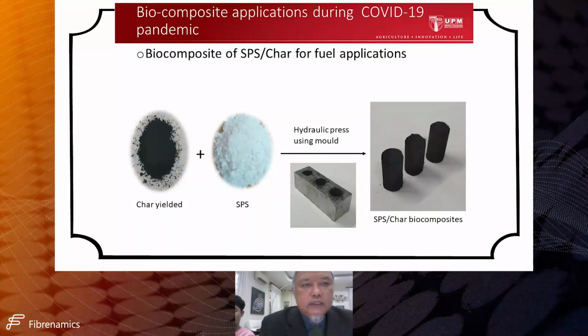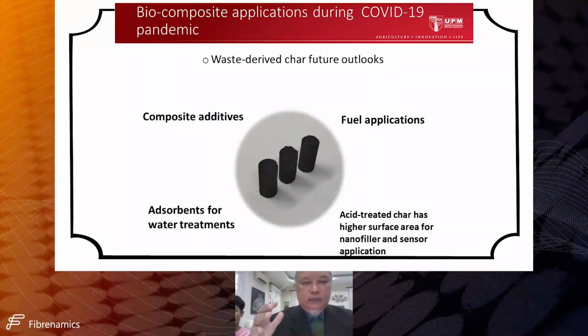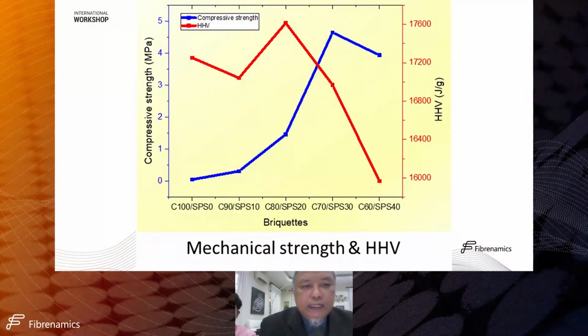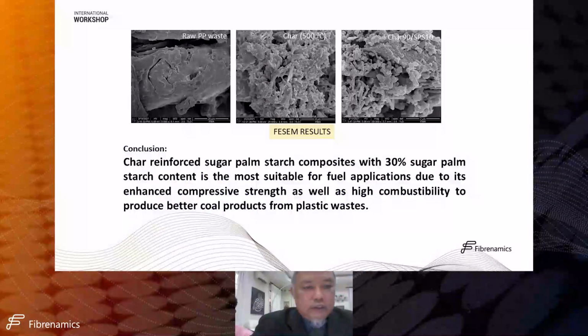The strength is good when you add more biopolymer, and the heating value is also not so bad. It's still good when you add biopolymer, meaning that biopolymer has so much contribution to this COVID-19 biopolymer composite. So we can conclude from this that char reinforced sugar palm starch with about 30% sugar palm starch content is, you can see, the most optimum, best suited for fuel application due to its enhanced compressive strength as well as enough combustibility to produce a better coal product from plastic waste.